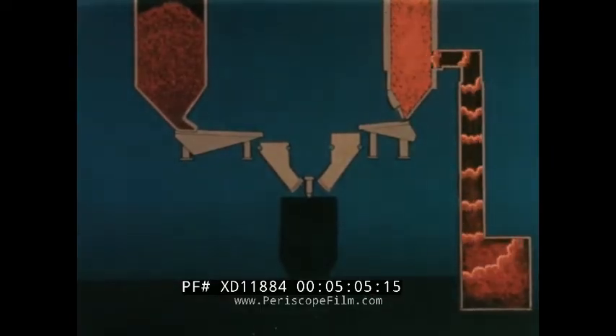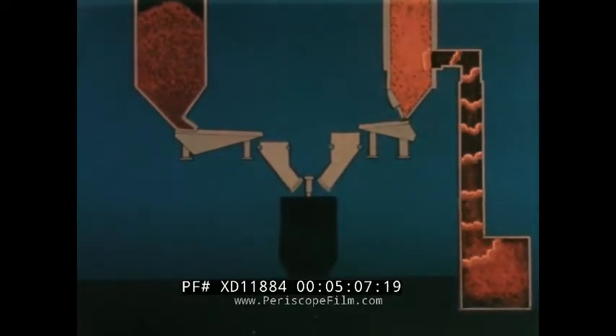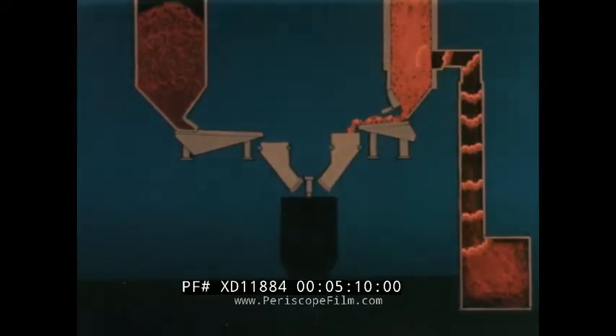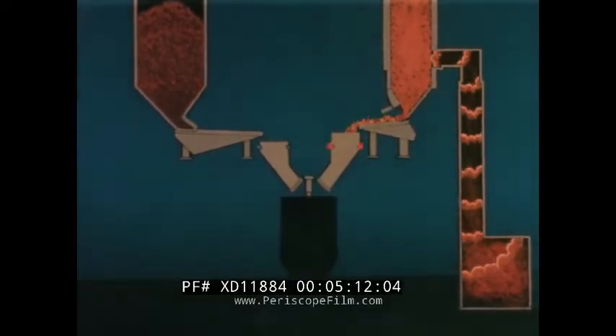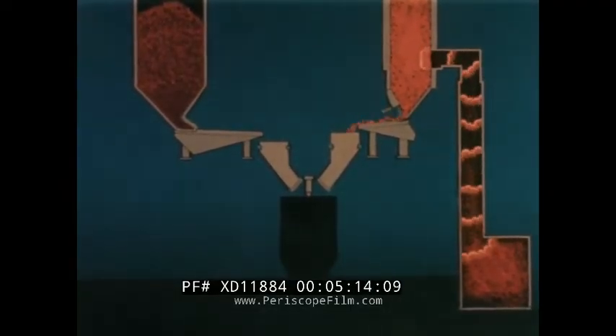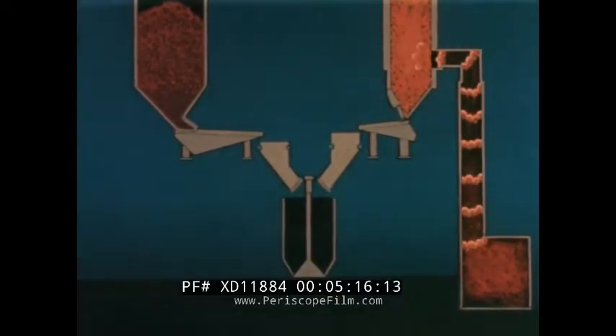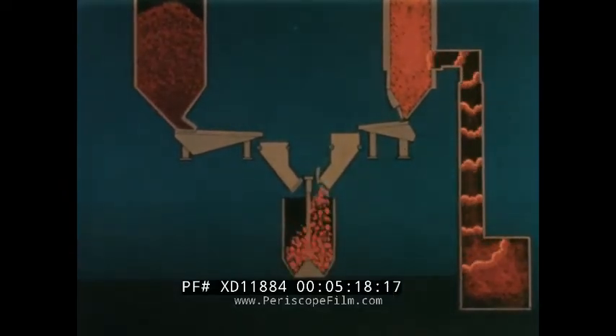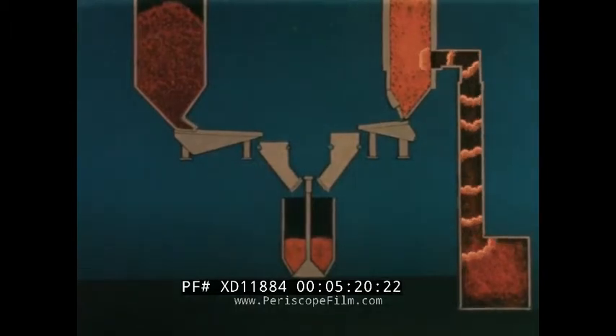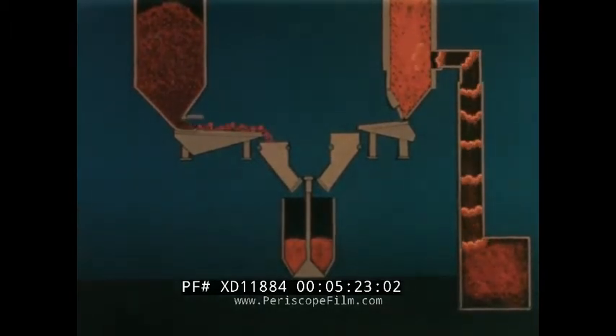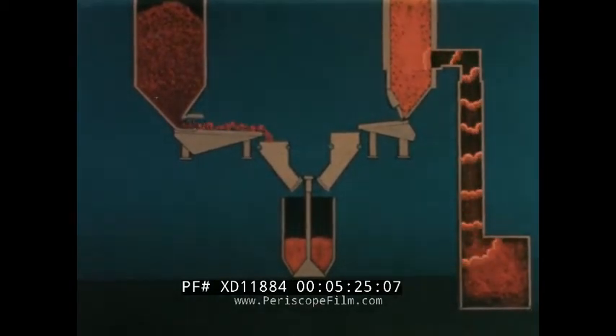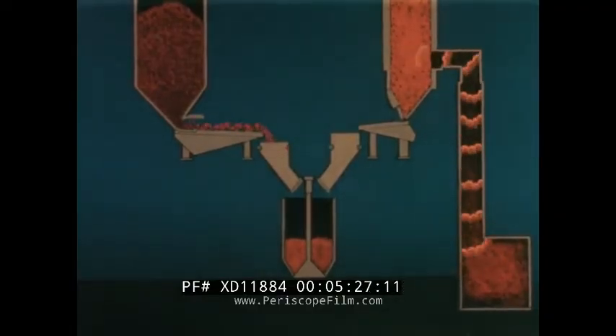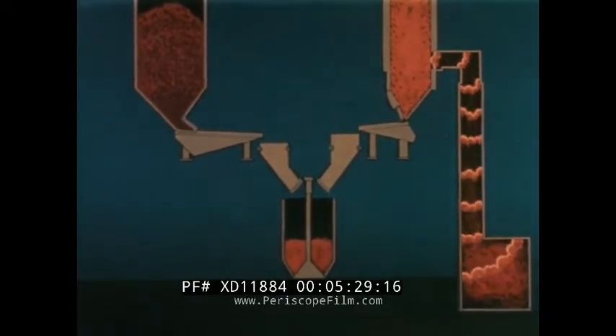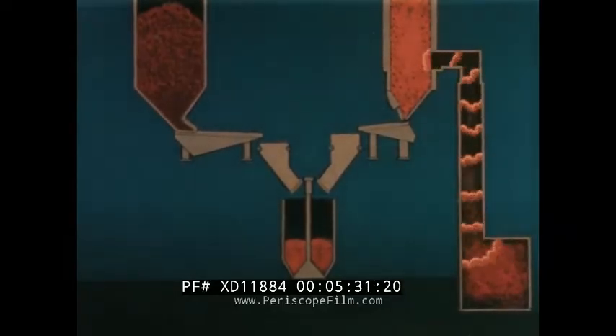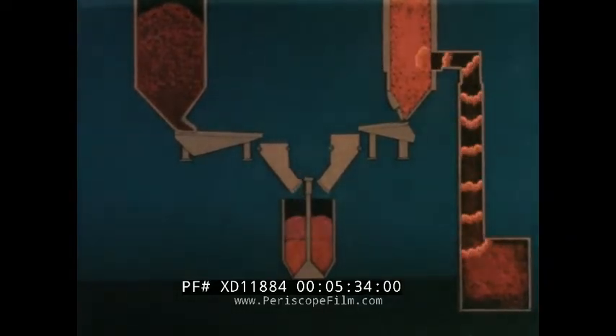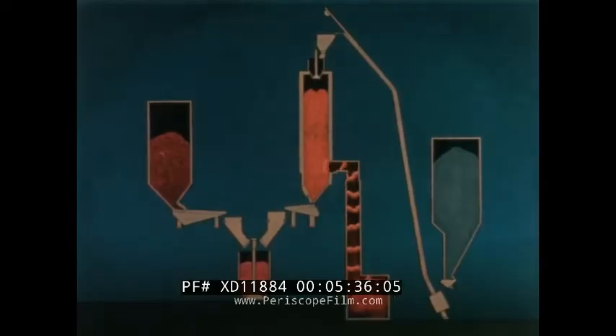After heating, the coke is discharged from the bottom of the preheater shaft via a vibratory feeder to an automatic system using strain gauge weighing. Sinter, the other raw material, preferably delivered hot from the sinter machine, is similarly fed into the charge bucket. The electronic weighing system, which measures the quantities of coke and sinter, is entirely automatic and ensures accurate proportioning of the charge for the furnace.